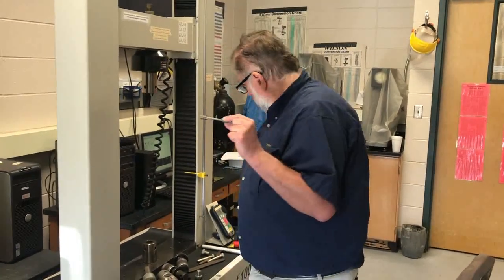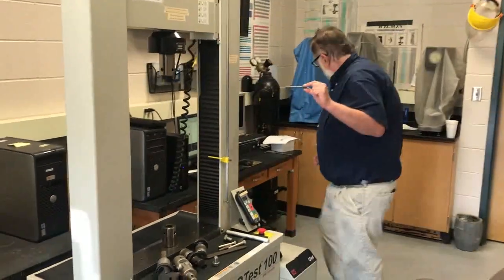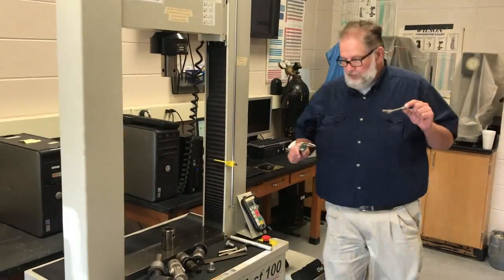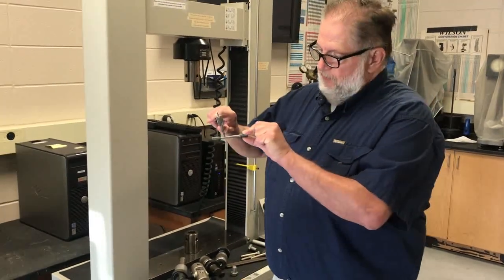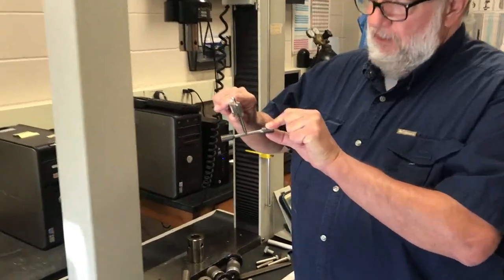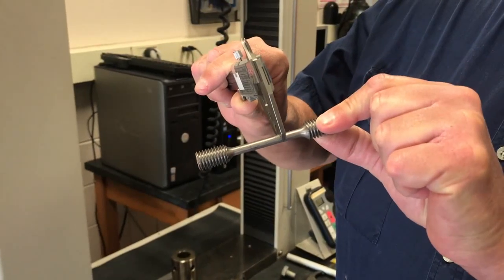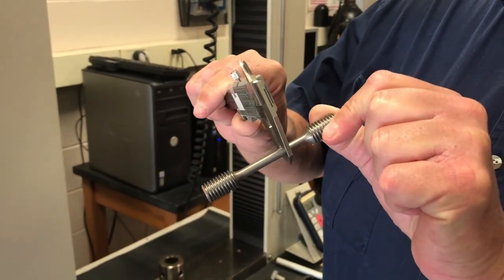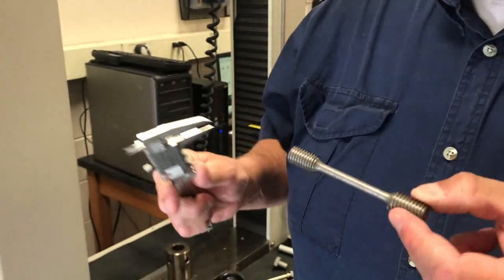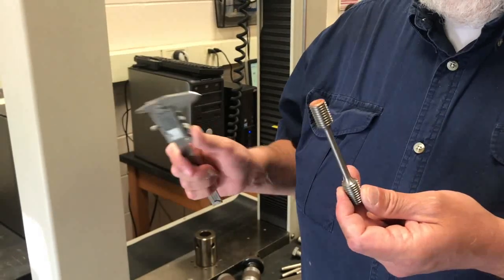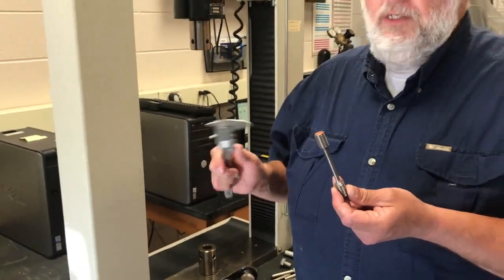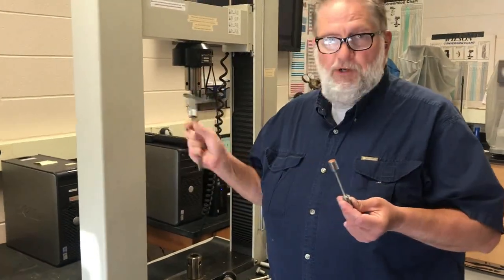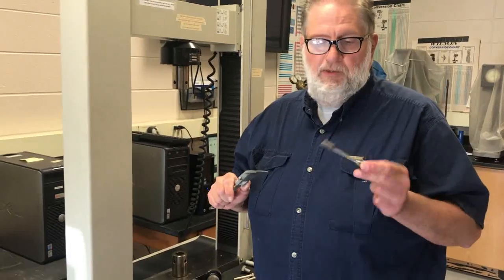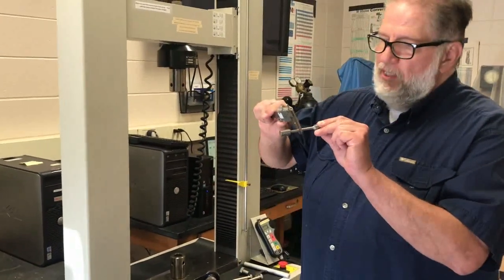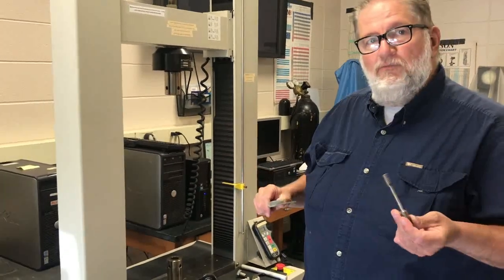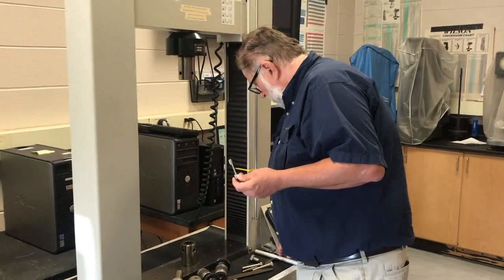The way you can determine that is to take vernier calipers and measure the diameter of the sample in multiple locations, turning the sample as you go, and then taking an average of the diameter. Now, of course, the cross-sectional area of the sample is the diameter halved into a radius, squared, multiplied by pi, but the software calculates that for you, and it will prompt you for the diameter. So measure the diameter in multiple locations, turning the sample as you go, take an average, and that's the value you enter in the software. So, set that aside for a minute.